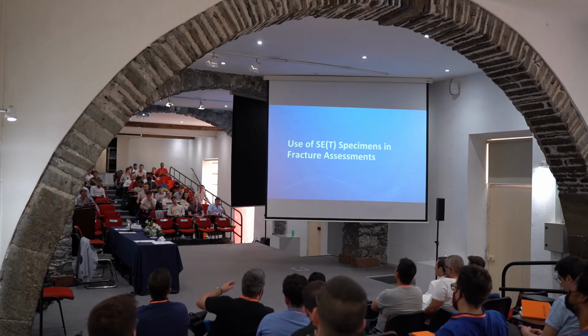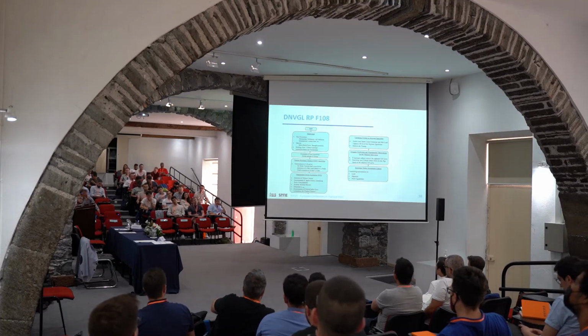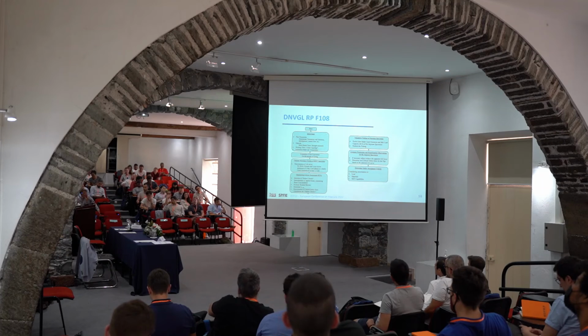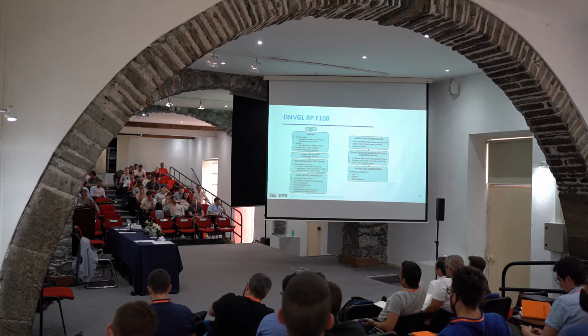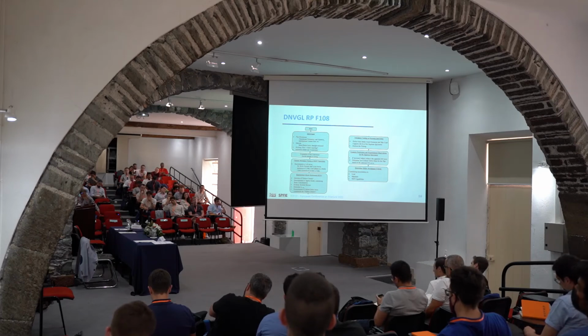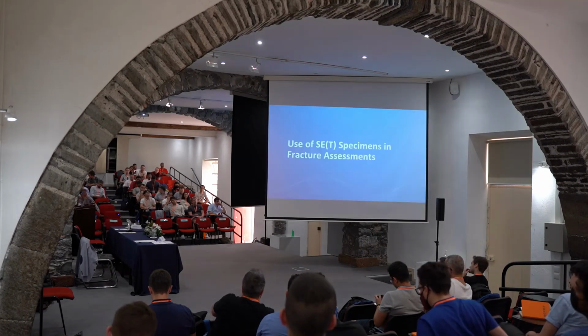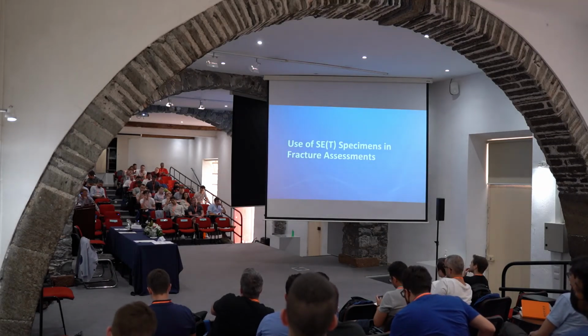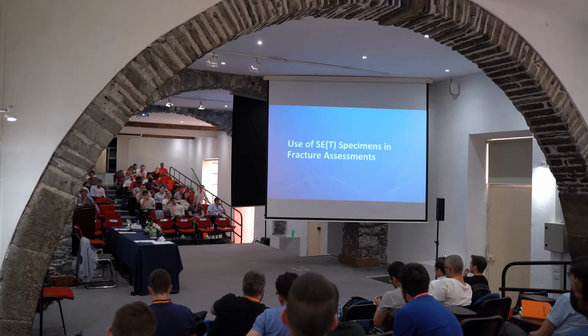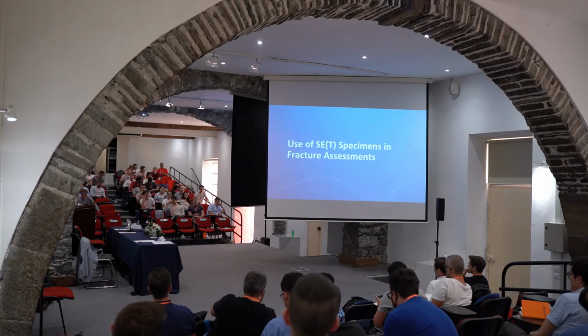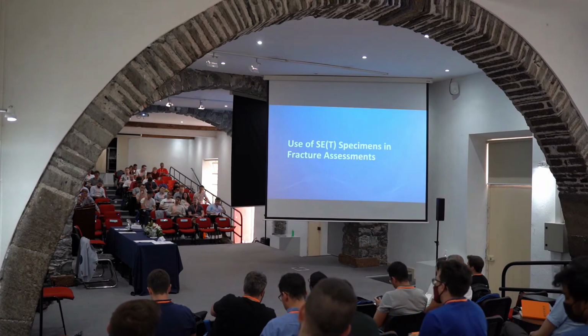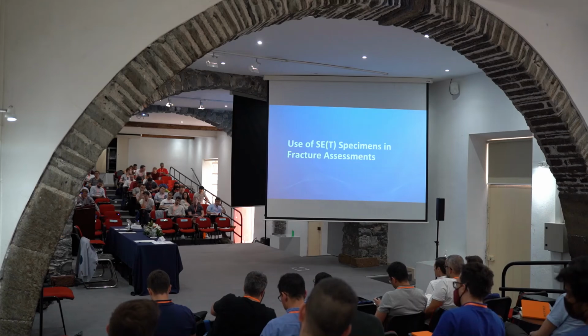One of the key ingredients in the DNV F108, which is the basis for any installation, any oil company in the world uses this for installation by girth weld, is the use of SE(T) specimens in practical settings. By the way, here in Europe, you call these SENT, which is single edge notched tension specimen. I'm not picky about terminology. This is ASTM terminology. I remember ASTM, so I will use that terminology. The committee E08 has normalized the terminology for fracture mechanics.